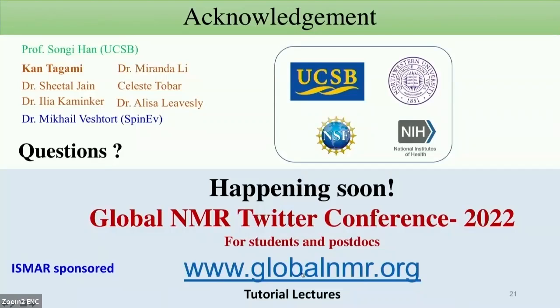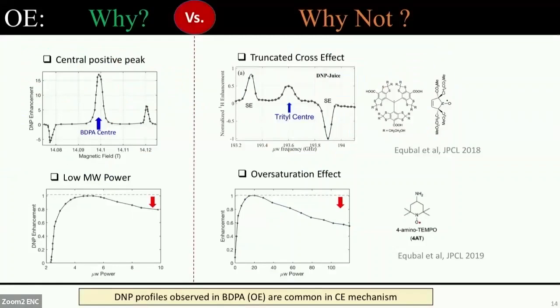One of the questions I had is you showed that microwave power dependence of the BDPA enhancement, right? That the enhancement decreases with increasing powers. Couldn't that potentially be explained by increasing temperatures? Can you comment on that? It's not temperature, because if it is temperature, then all the, say, solid effect would also go down with higher microwave power. But the solid effect increases. It's only the central DNP profile that decreases with higher microwave power. So it's not temperature.